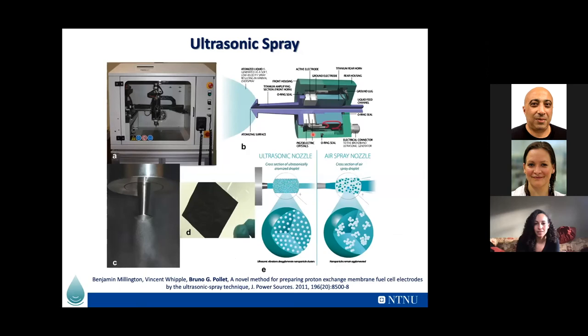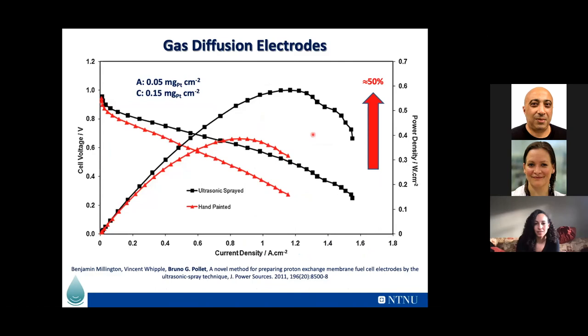Sonotech, where we looked at different types of ultrasonic spraying systems, going from 20 kilohertz to 200 kilohertz. And we looked at lowering the loading of the anode and cathode sites. What we've actually discovered is that by using this ultrasonic spray technique, we could increase the performance by 50%. The good thing is that we could also lower the loading of the platinum to get similar performances, which is very interesting.